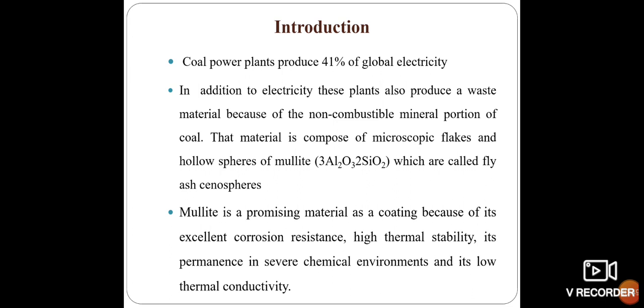Mullite is a promising material as a coating because of its excellent corrosion resistance, high thermal stability, its permanence in severe chemical environments, and its low thermal conductivity. When compared to the current thermal protective coatings, which are based on yttria stabilized zirconia, it has a much lower coefficient of thermal expansion.